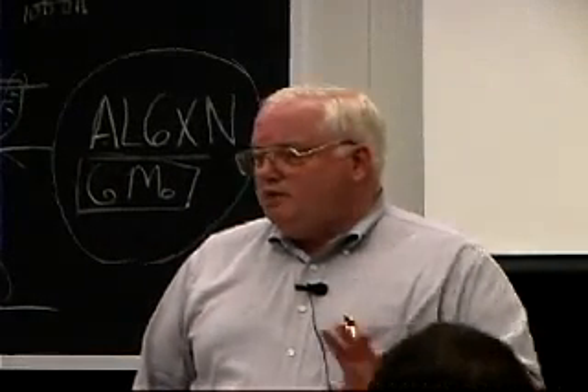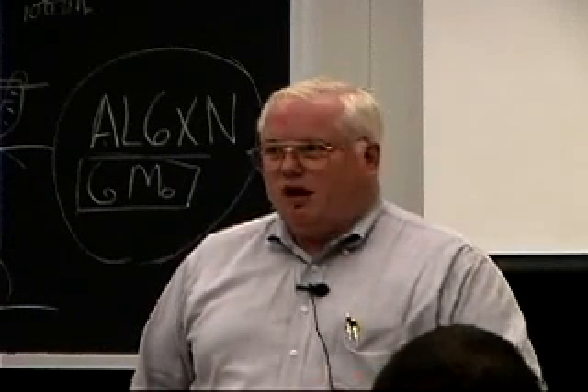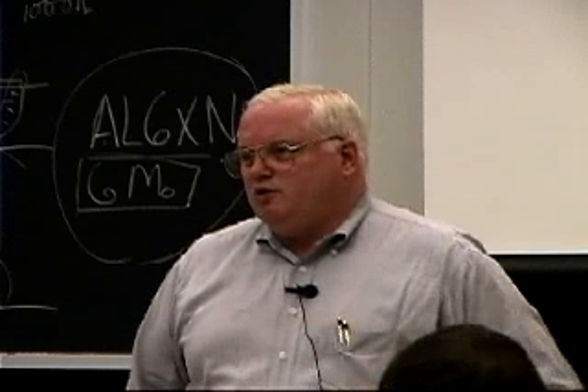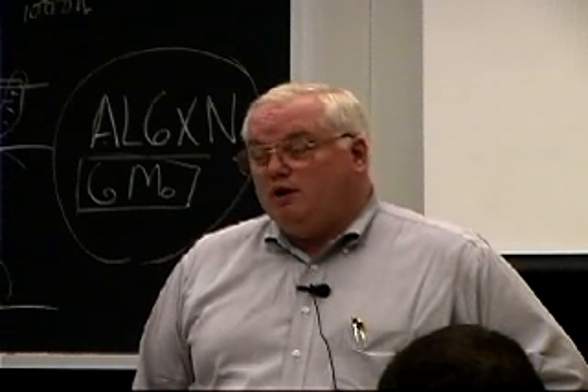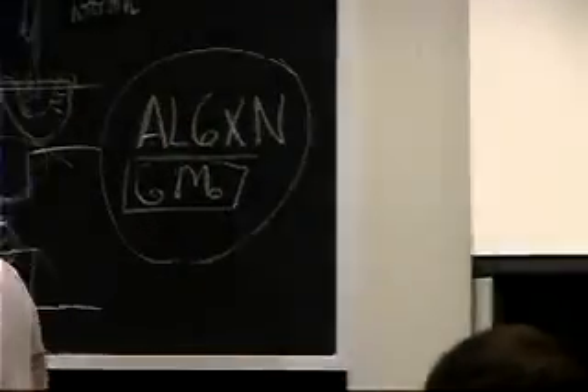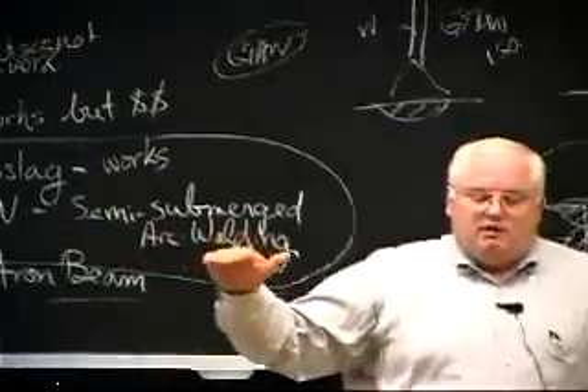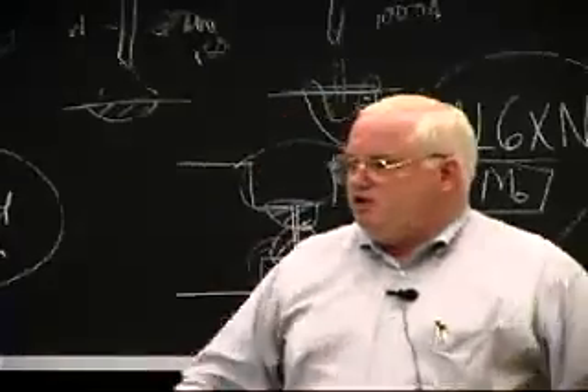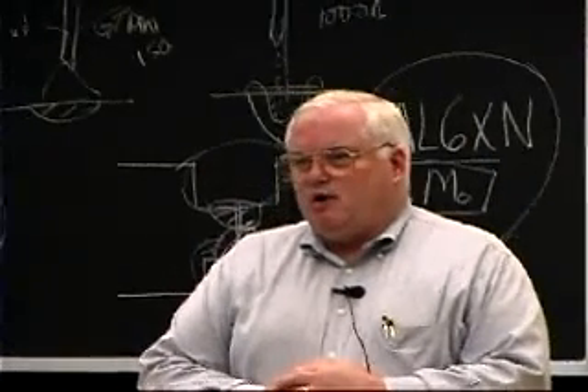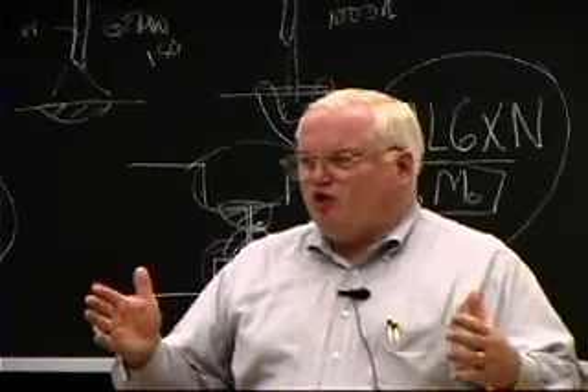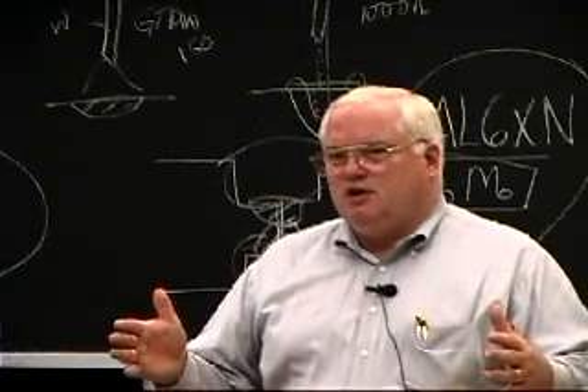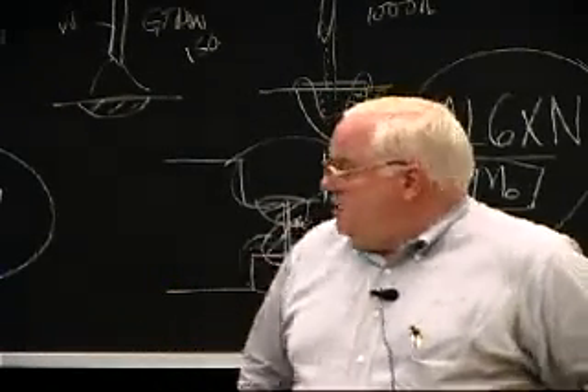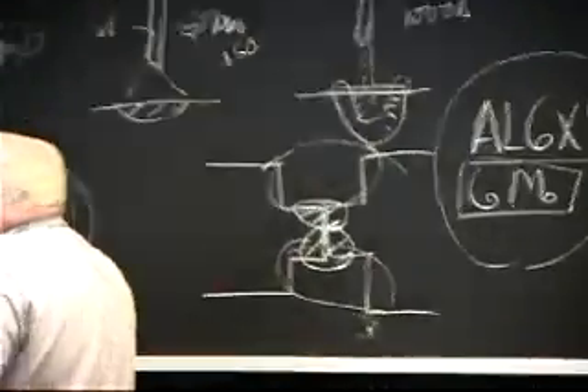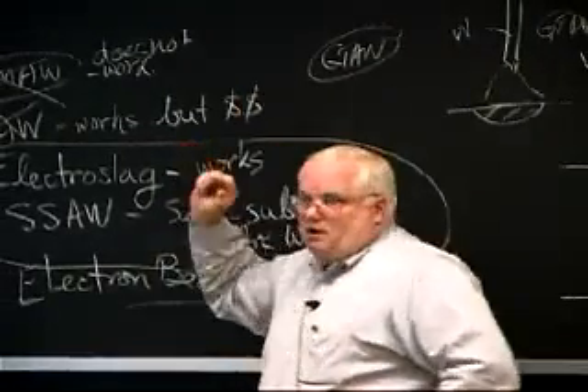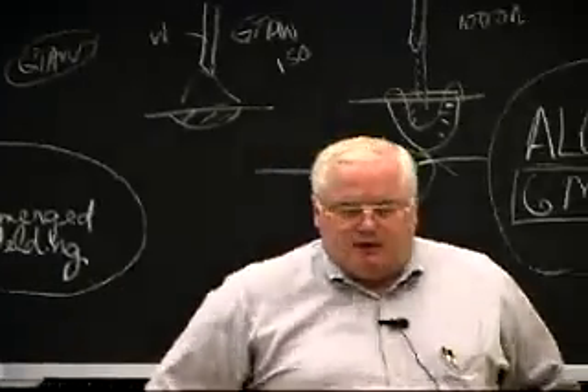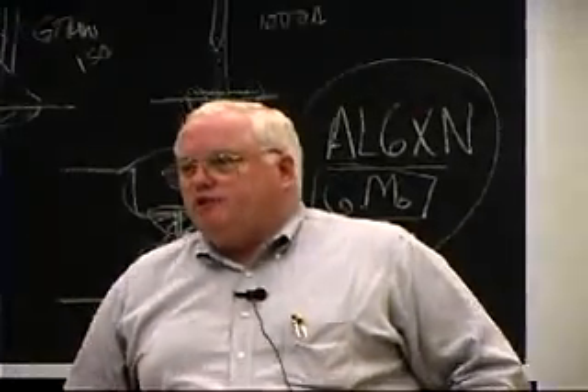They built aluminum submersibles, which are even better, but again, you get tremendous distortion problems. And we don't even have these types of heavy section welding technologies for aluminum. When General Dynamics built the big aluminum spheres for the LNG tankers, they basically used gas metal arc welding, and they were welding 24-inch thick sections at the equators of these big spheres. And that was quite a technology to do that. So you can build big thick aluminum structures probably by gas metal arc or electron beam, but the costs get to be prohibitive there too.